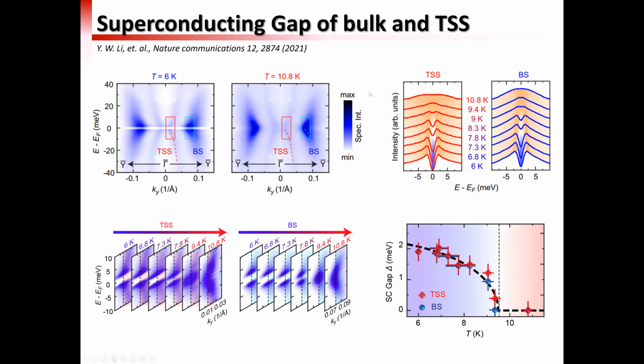The reason we cannot go lower is that there are a few reasons. One is that the temperature is still not very low, and also the laser. Even though our laser is a quasi-continuous laser, the resolution is still around 1 meV, and coupled with the temperature and some surface variation, that contributes to the overall 1.5 to 2 meV resolution.